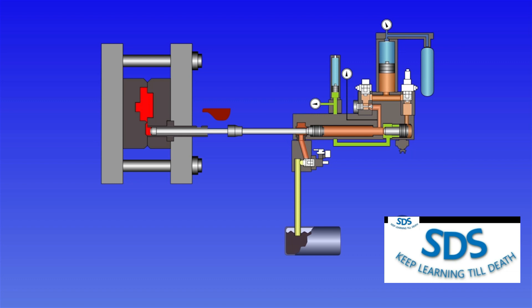Typically, pressure-tested castings may require up to 900 bar of applied pressure to ensure that there are no leaks from the component. Second, it is essential to control the speed at which the intensification piston moves.